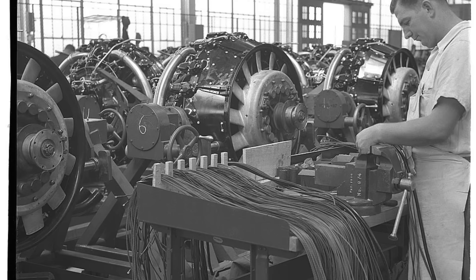Thompson knows that understanding why these transmissions fail could give the Allies a critical advantage. The fractured gear is enormous — 7 inches in diameter, 2.5 inches thick — designed to transmit incredible torque from engine to drive sprockets. Thompson begins a meticulous examination, measuring hardness using a Rockwell tester and pressing a diamond cone into the steel surface. The reading is 63 HRC, far above the specification of 58–60 HRC for Panther transmission gears. A gear too hard is a brittle gear: it resists wear, but fails catastrophically under stress. Every sharp maneuver, every sudden halt, every battlefield shock load could snap it instantly.